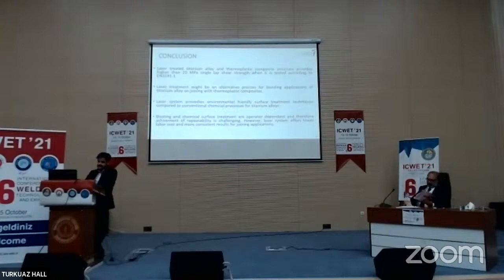And also laser treatment might be an alternative process for bonding applications when joining titanium alloy with plastic composite. Laser systems provide environmentally friendly surface treatment techniques compared to conventional chemical processes for titanium alloys. Blasting and chemical surface treatments are operator dependent, and therefore achieving repeatability and consistency is challenging. However, the laser system offers lower labor costs and more consistent results for joining applications.